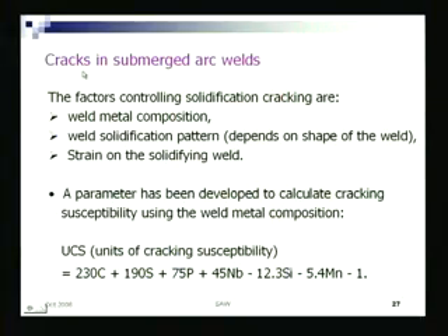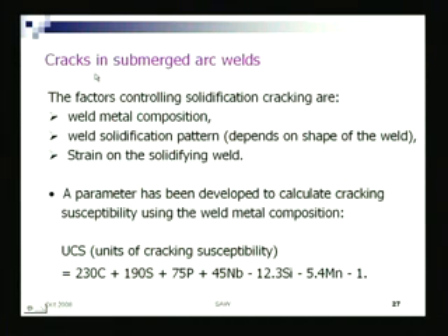At the same time, there can be a risk of cracks developing, because it is also a high heat input welding process. Though being automated I can increase the speed, it depends on how much deposition rate you want, and deposition rate again depends on the speed. If you want higher deposition, you will have to reduce the speed. Once you reduce the speed, your heat input rate increases, and that increases the chances of cracks forming in the weldment. That is how we see the factors controlling solidification cracking.